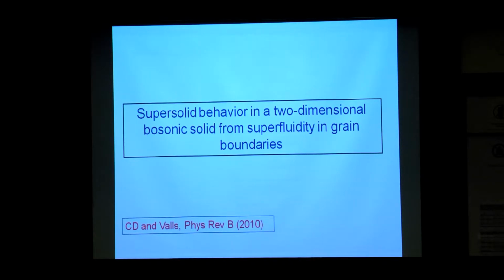So the first calculation that we did was for a system of two-dimensional bosons, and what we tried to show was that if I look at this two-dimensional system of bosons under appropriate parameters such that the system is in a solid state, solid meaning it's a two-dimensional solid, but it's not a perfect solid, it has grain boundaries, then that system can exhibit behavior similar to what was observed in the experiments on helium. That can also show this non-classical rotational inertia under certain circumstances.